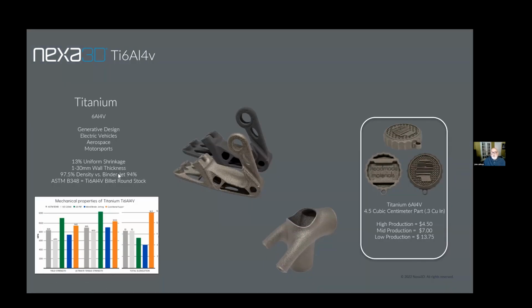So with titanium, for example, using the Headmade cold metal fusion QLS process, we're going to print with titanium, and we're going to sinter after the fact, which I'll show all of that in great detail in a moment. The beauty of the way this system works is we have uniform shrink in all axes of about 13% for titanium, which is outstanding. The other beautiful thing is we're going to be able to do thicker, chunkier parts than we would ever want to do with DMLS. So we can get up to 30 millimeter wall thickness or down to 1 millimeter wall thickness in some cases, and still produce parts that are 97.5% dense and have better mechanical properties than billet machining.